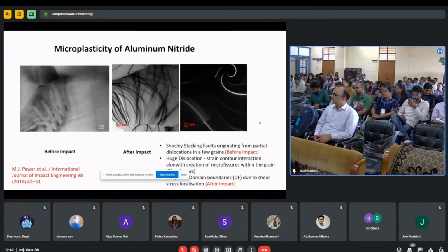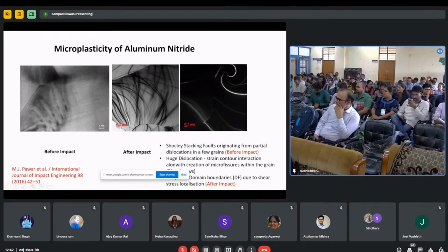But when shock waves come, with shock wave pressure of 50 gigapascal, 50 GPa or 40 GPa, this brittleness doesn't play any role. What happens is that ions are forced to move from one place to the other, and you get dislocations like this. And it is not only dislocations, you get domain boundaries also.